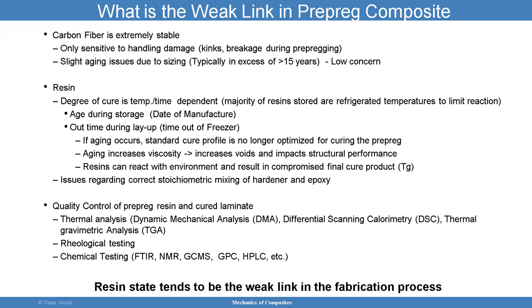Aging increases viscosity, meaning things are not flowing as smoothly. And since things are not flowing as smoothly, it increases the voids and it can impact structural performance. Just take glue from the store. If you leave it out for a long time, I don't expect it to be as viscous. Things may not glue as well. Does that make sense? So resin can react with the environment. Also, that's another thing that can happen and result in a compromised final cure product.